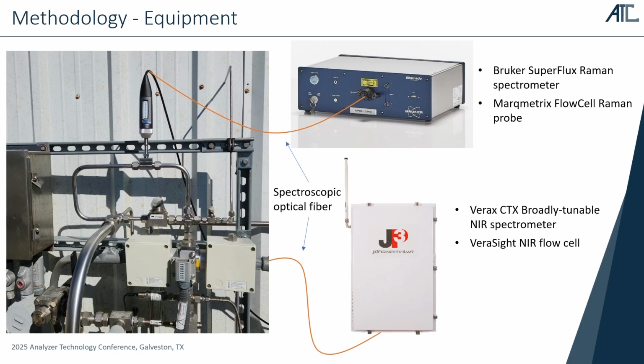And we used a Marqmetrix flow cell Raman probe because that's what I had on hand at the time. But we've got that hooked up immediately in series on a fast loop with a JP3 Verax near-infrared spectrometer using the JP3 VeraSight NIR flow cell. So both measurement points are on a fast loop. We're measuring gasoline, and they're directly in series with each other. So it goes just around like that and gets returned to the process.